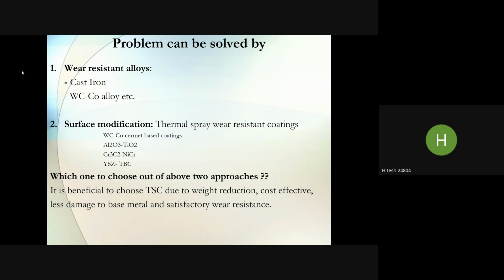So what is actually happening over there? Heat dissipation. But in the case of an internal combustion engine, that dissipation is not required, because heat is required for efficiency. So to avoid the heat loss, we have to use some thermal barriers, and this material is widely used, that is yttrium stabilized zirconia. Other than this, there are some other materials I recently came to know about, refractory high entropy alloys, because we are in the process of filing a project in ISRO. They have mentioned an ultra high temperature application, where the minimum temperature is 1500 degrees Celsius.